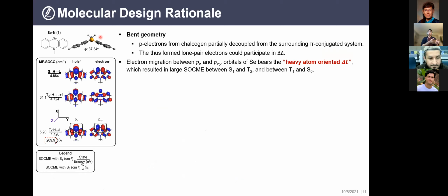We designed our molecule series to have a so-called bent geometry. In this specific molecular scaffold, if it were fully conjugated and fully planar, the non-bonding electron of the selenium, which is a heavy atom, would be fully conjugated with the surrounding pi system. But because it's bent, the p electrons from the selenium get deconjugated, and they are now so-called non-bonding electrons. In the first triplet state, T1, of this so-called SeN, because we have nitrogen here, the T1 to S0 transition is characterized by a pz to pxy, or out-of-plane to in-plane transition, directly centered on the selenium heavy atom. And from the calculation, we have a super large spin-orbit coupling value among purely organic materials.